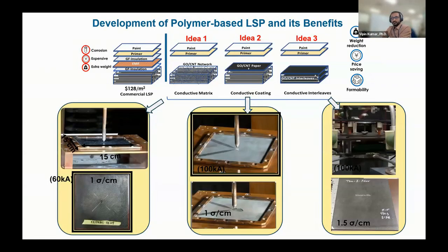So in my research, I tried to do all polymeric, no metal, lightning strike protection. I have 3 different approaches which I tried. One is I can make the whole matrix itself conductive. The second one, I put a conductive polymeric layer on top of it. And the third, I can try to enhance the electrical conductivity of the whole laminate by having interleaves, either with nano fibers or just carbon fibers.